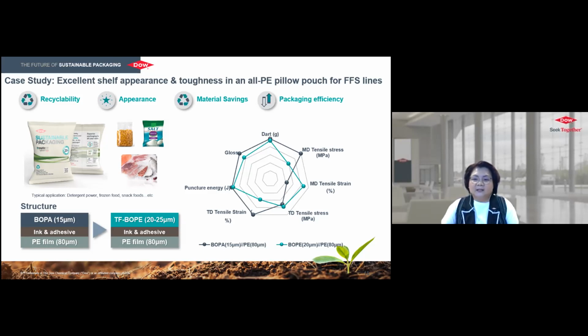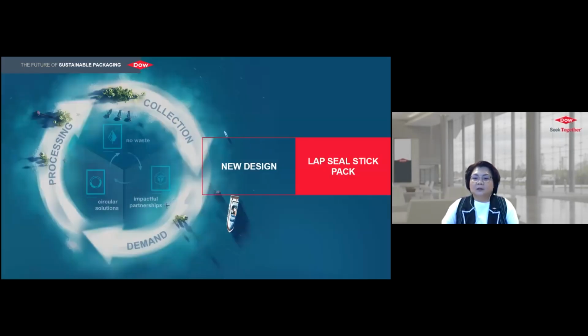This will not significantly impact the performance of the pouch, and in fact, the tensile strain of TF BOPE-based laminates is much lower than BOPA laminates, which helps to prevent undesirable elongation issues, which may result in delamination and other related problems. Such structure is applicable to detergent powder, frozen food, and also dry food packaging. So the last packaging format which we will cover is a very new innovation from Dow, Lap Seal Stick Pack, targeting material savings and performance.